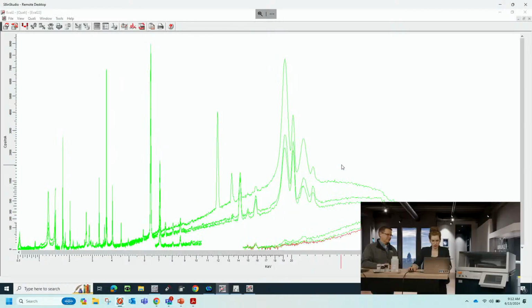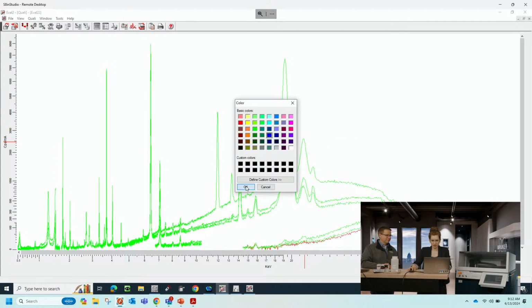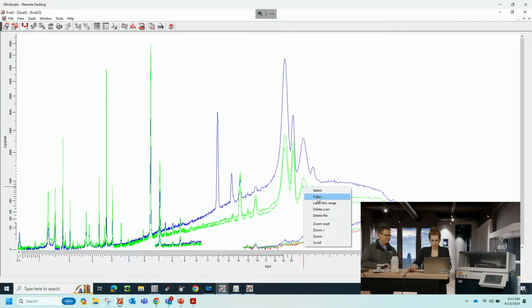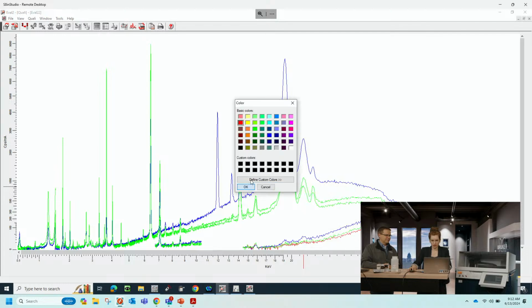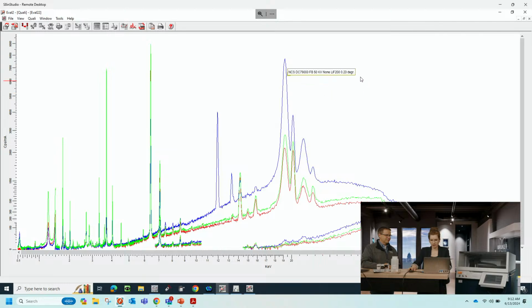Okay, now we can show it. So this is very green. I'm going to change the colors a little bit so that we see that. So the blue one is my fuse bead. That's why it says FB. Why is it so high here? Because this is my Compton peak. The Compton peak is very susceptible to the overall Z number or atomic number of the samples. So the lighter my matrix is, the higher the Compton peak is, which is also very interesting in terms of using it as an internal standard. But that's going a little bit too far off topic.